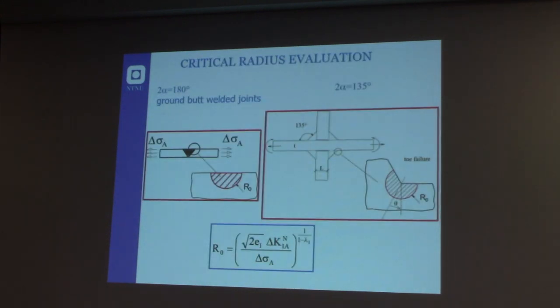We defined for the weldments the same consideration that we made before for static loading. We consider a welded material without any geometrical discontinuity, and this is the critical radius. So the energy of the unnotched component has to be equal to the energy close to the notch tip of the notched component for determining the value of the critical radius. So you always need two pieces of information.